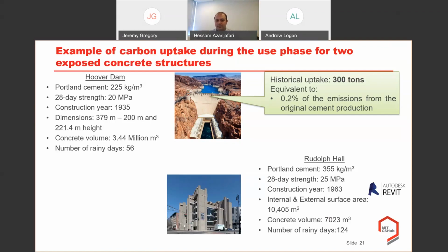The other example that we used was Rudolph Hall at Yale University. It's an exposed concrete structure which was constructed in 1963 and follows the Brutalist architecture principles, and there's no coating on the outside or the inside of the concrete elements. Therefore we have two types of exposure condition. We extracted the site plan data by Autodesk Revit software, and we have a precise estimation of the exposed concrete surface area, both internal and external, which was around 10,000 square meters. We also had the concrete volume around 7,000 cubic meters.